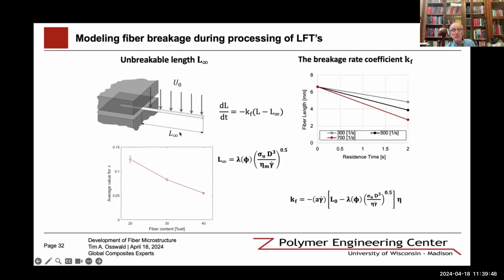that would be the corresponding infinite length for those conditions that have a fiber viscosity and matrix viscosity and a fiber with a different fiber property. So you can see the equation for L infinity has the ultimate strength of the fiber, the diameter of the fiber, the viscosity of the matrix, and the rate of deformation that lead to some standard, not including fiber interaction. Then, of course, lambda as a function of phi is a fitting parameter that takes into account the fiber content. You can see that parameter goes down as the fiber content goes up. So that's the average value of lambda for various experiments.